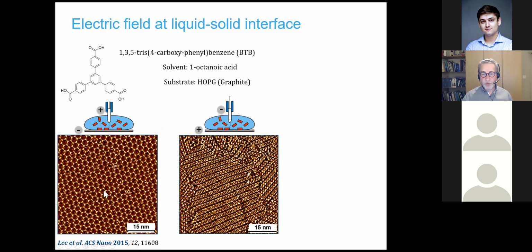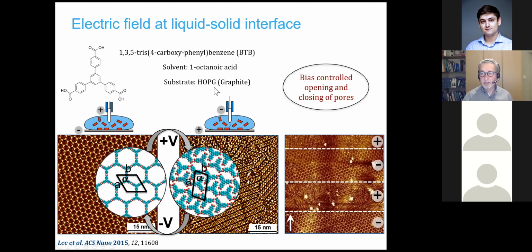Under conditions where the substrate is positively biased, we get a porous network, as shown over here, where each of these small triangles is actually one such molecule. So they form a porous honeycomb type network sustained by hydrogen bonding. If we now switch the polarity though, we get a high density network. All of that is on HOPG, graphite, using octanoic acid as solvent.